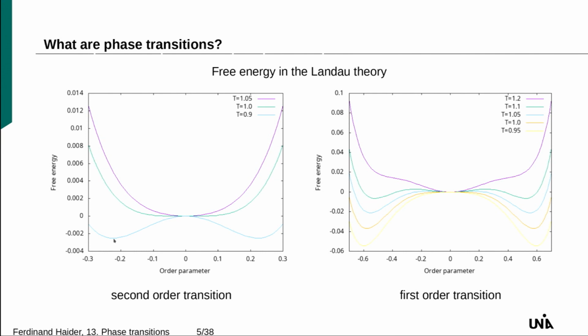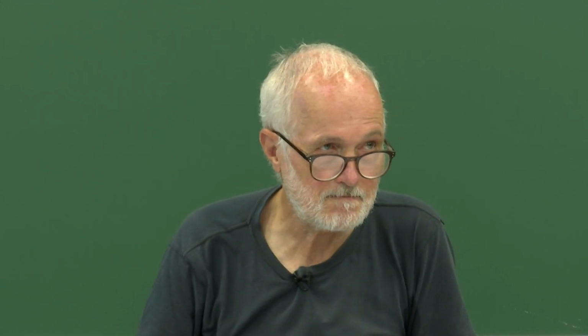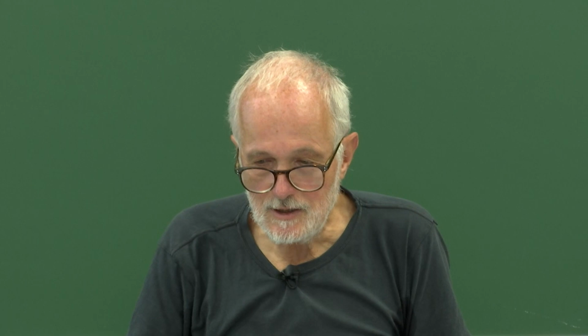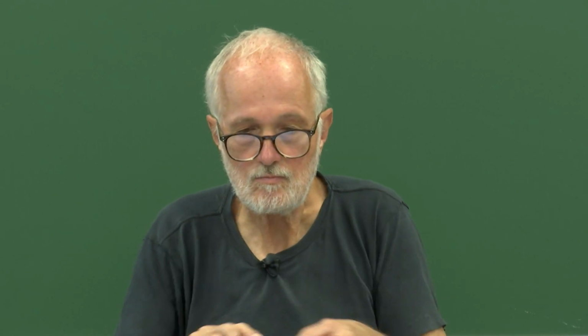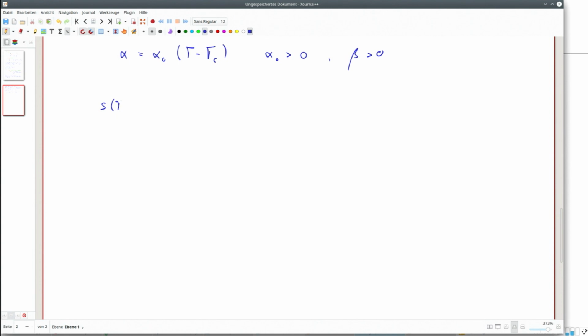But what does it mean? If we say the free energy or free enthalpy is minimized, it means for temperature above or at the critical temperature, the equilibrium order parameter is at 0, so the system is completely disordered. As soon as we go below the critical temperature, there's a finite degree of order. If you think of a magnetic system, there can be magnetization upwards or downwards—that's why we have these two minima. And this can be translated into an equilibrium order parameter, psi.